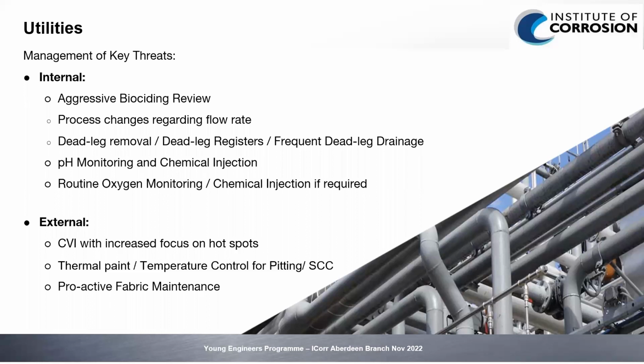For external, we feel a renewed focus on hotspots is advised for dealing with CVIs. Obviously, 100% CVIs are expected, but making sure extra attention is paid to these hotspots will ensure anything is identified and managed. For the CRA locations, we recommend looking at process control first to see if the CRA equipment can operate at a lower temperature and still operate as desired. If that is not possible, thermal paint may be the best option moving forward to keep pitting and cracking at a minimum. Finally, we also suggest some proactive fabric maintenance to combat general external threat. Again, this is something we feel can have real value for your client.